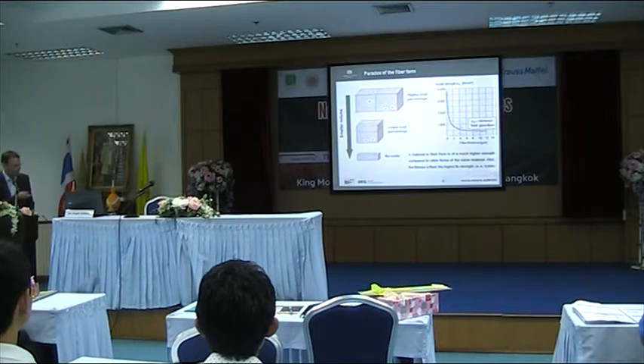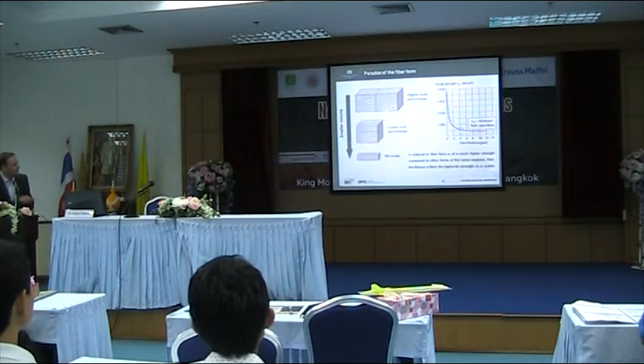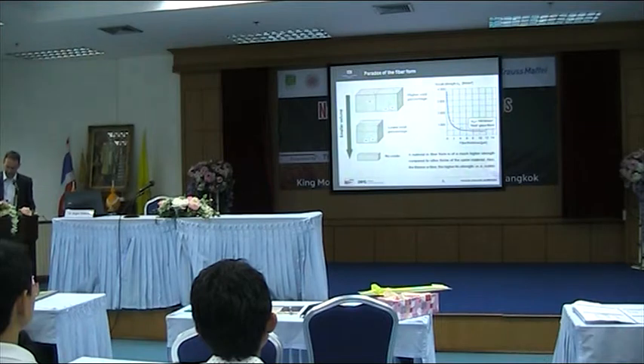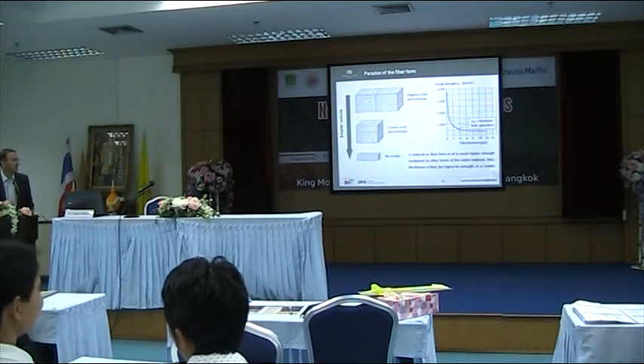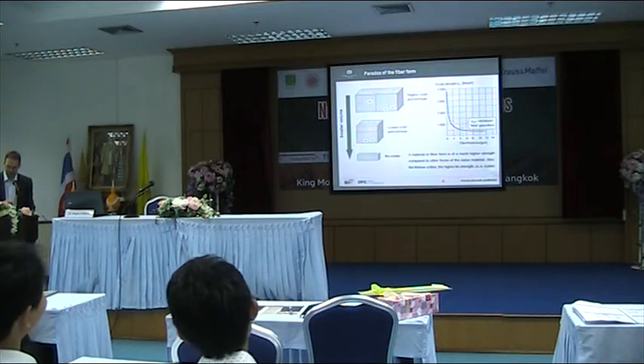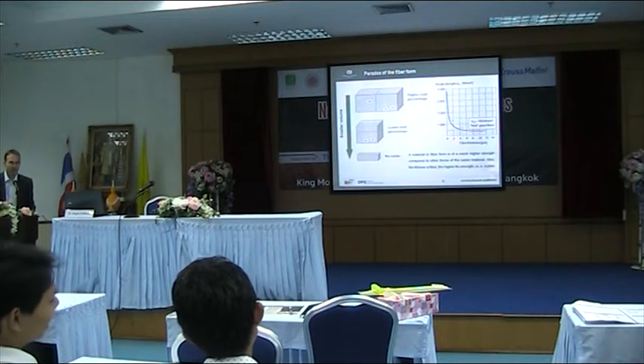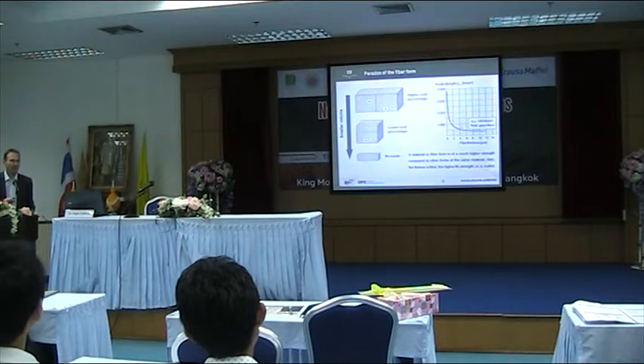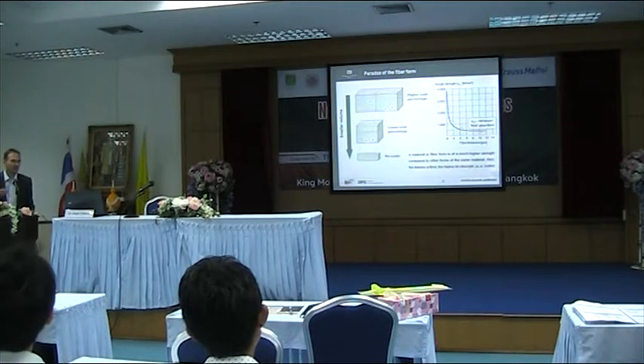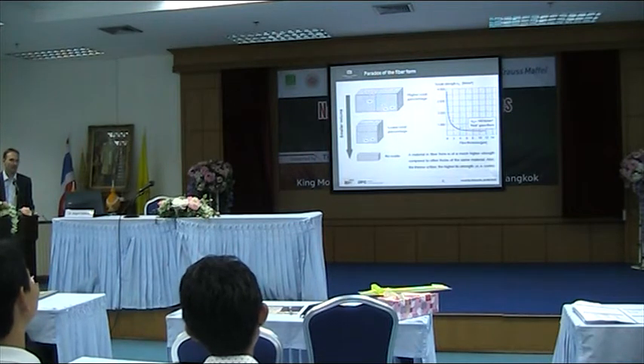So the lower the material geometry, especially the lower the diameter of a material until we come to a fiber form, the higher the specific strength and also the specific tensile modulus. So this is something ruling for all materials in a fiber form, but especially interesting for our reinforcement fibers, glass fibers, carbon fibers.